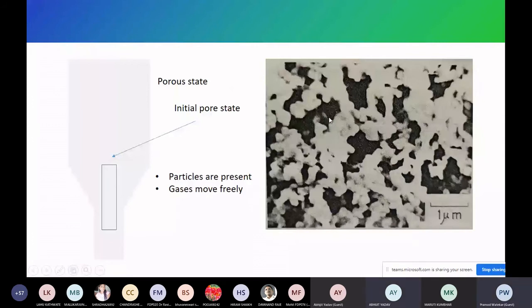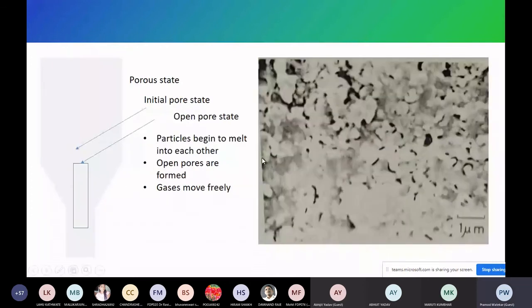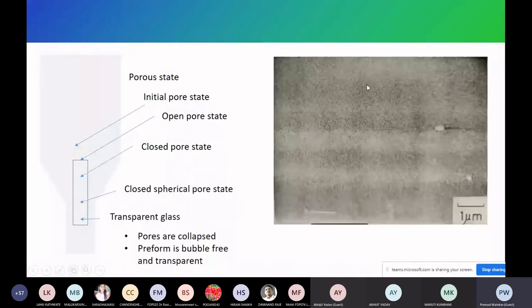You can see this soot to the naked eye looks very good, white colored soot, but if you go micro, there are many gaps here, and it can trap air or oxygen or helium or any gases. If you make glass from this soot, this trapped air or trapped gas can form bubbles. So bubble forming is a huge problem in the glass industry. To avoid this, we send helium there. Helium generally has a tendency not to form bubbles up to 500 micrometer gap. I will show the last picture here. When you heat it in the furnace, after heating, it became very clear glass.